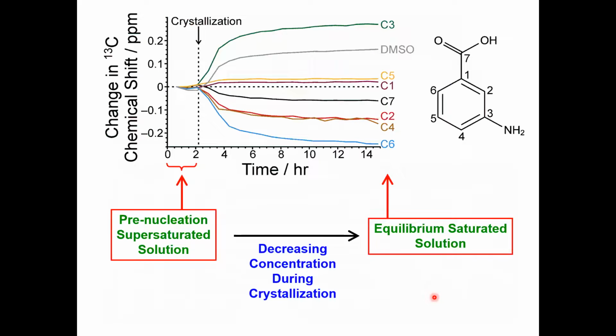Okay, so what we have at the end of the crystallization experiment is an equilibrium saturated solution. What we have at the beginning in this 2 hour window is what we call a pre-nucleation supersaturated solution. That's a thermodynamically unstable solution because it wants to crystallize, but it's just trying to find the right mechanism, the right nucleation pathway to allow the crystallization to happen. And this represents a decrease in concentration, as I described earlier.